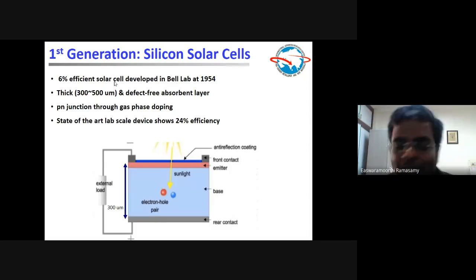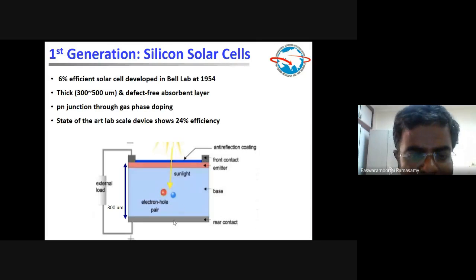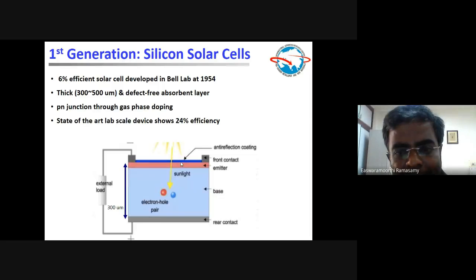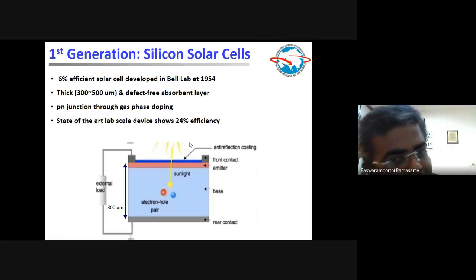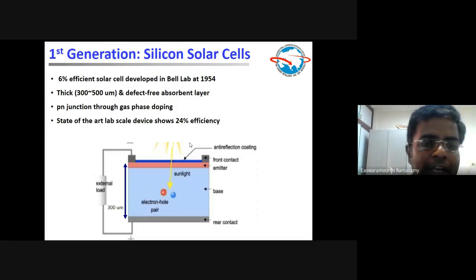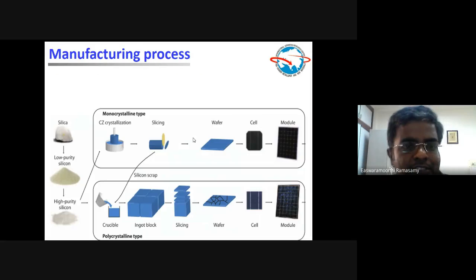The first cell, built in 1954 at Bell Laboratories, was about 6% efficient. But a lot of science and development activity optimized all these interfaces, the junction, and the quality of the material, and how to collect the carriers more effectively before they recombine. Value-added components like anti-reflective coating and easy-to-clean coatings were added. The efficiency of the current state-of-the-art device is more than 25%, and commercial scale modules perform close to 20%. That is the status of first generation silicon solar cells.